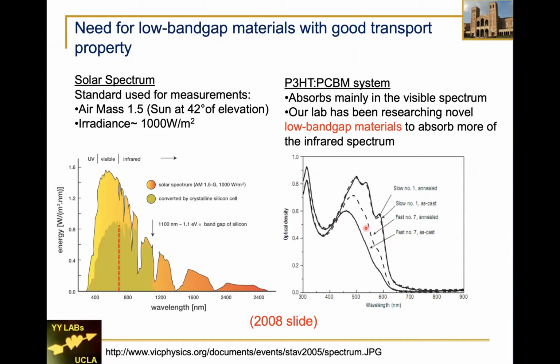We pushed the device efficiency from 1% to about 5% in the Nature Materials paper. The paper has been cited more than 6,000 times now, a very highly cited paper. But I want your attention to this. This is the absorption edge. By looking at this absorption edge, one can immediately see what is missing. This is the solar spectrum, but this part, 60% of the energy, is infrared light, not being used. P3HT only utilizes the visible part.